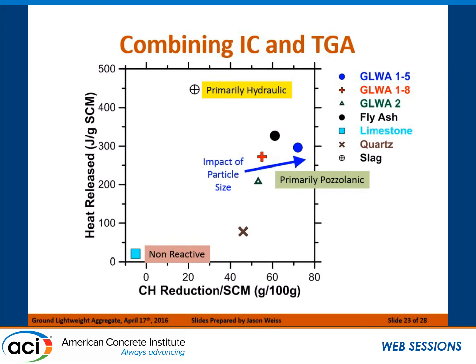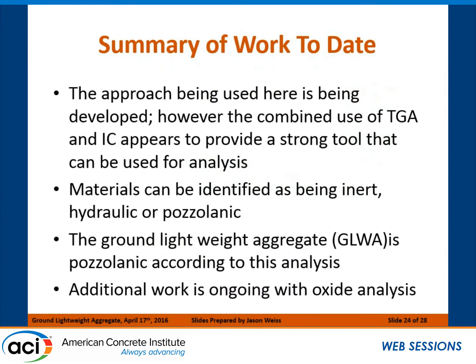And then all of a sudden we can see the quartz, right, may have some effect here, but really a lot of calcium hydroxide, low heat. And then all of our pozzolanic materials sort of falling into this nice cluster here, where as we start to change the particle size, we move a little bit over to the right-hand side, likely because we're not at complete 100% reaction. And this is one of the things we're really working on, is to figure out how much of the products are left when we're all done.